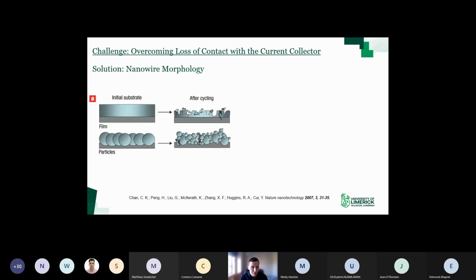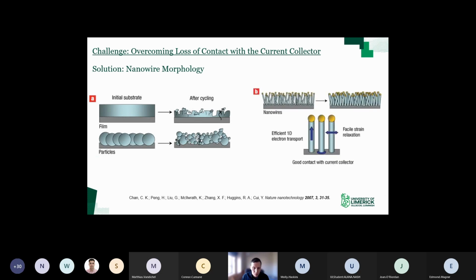Okay, so if we look at the first challenge then, overcoming the loss of contact with the current collector related to the volume expansion. Like I said, if you use micron-sized particles or films, basically all you get is pulverization. The seminal work on the use of nanostructured silicon was done by Professor Yi Cui at Stanford back in 2007. He published this in Nature Nanotechnology. He put forward the use of silicon nanowires instead of films or particles.